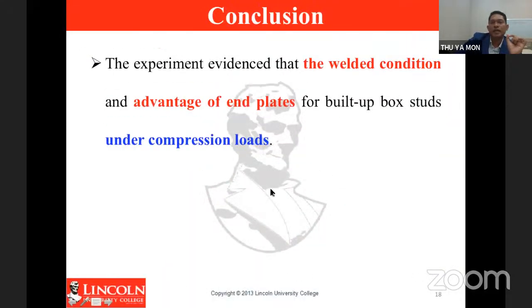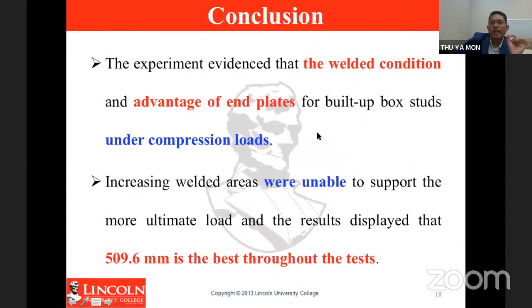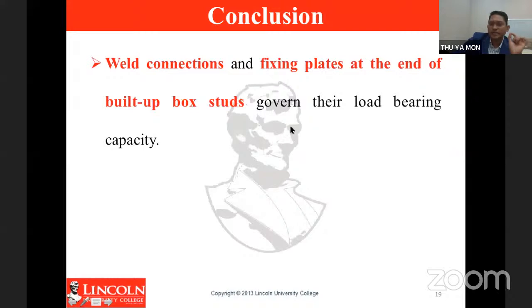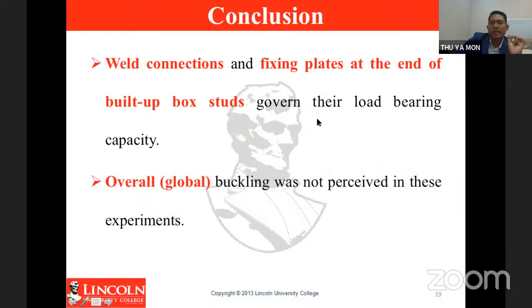For conclusions, this experiment is evidence of the advantages of welded connections and the use of end plates for built-up box columns under compression loads. Also, increasing the weld areas was unable to support more ultimate load, and the results display that 509.6 millimeter is the best spacing of the test. These experiments demonstrate that two factors govern the load bearing capacity: welded connections and the application of fixing plates at the ends of the built-up box studs. Throughout the experiment, no overall or global buckling mode occurred.